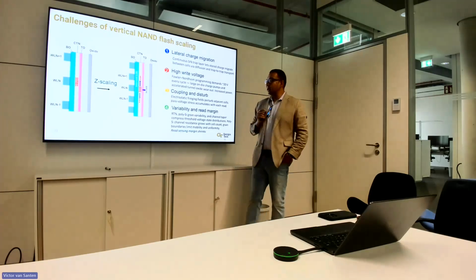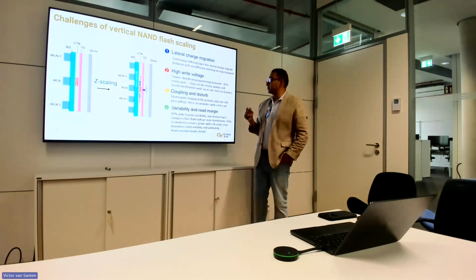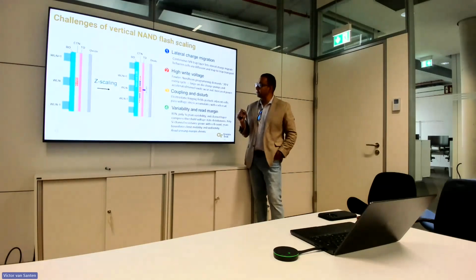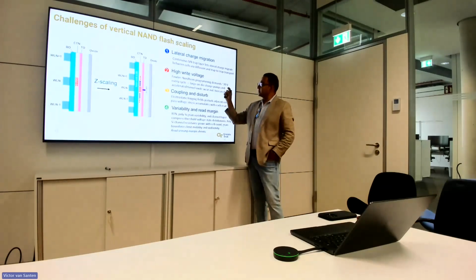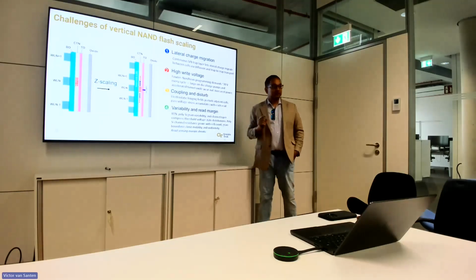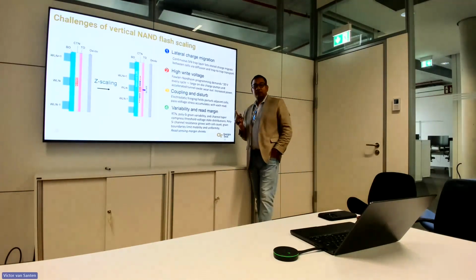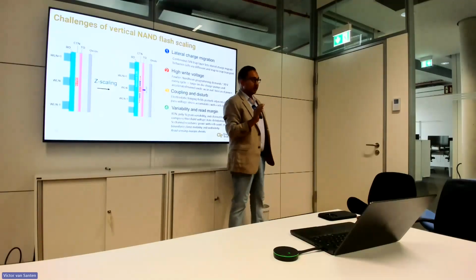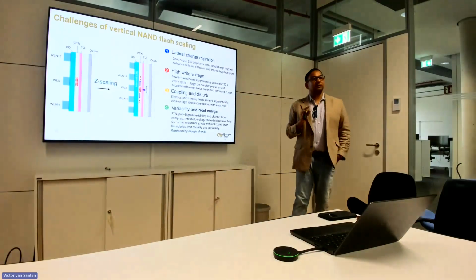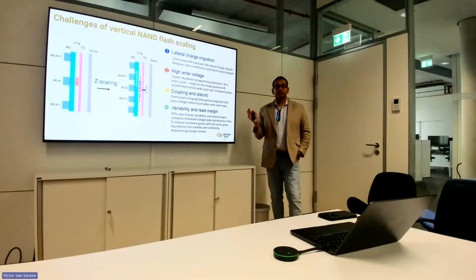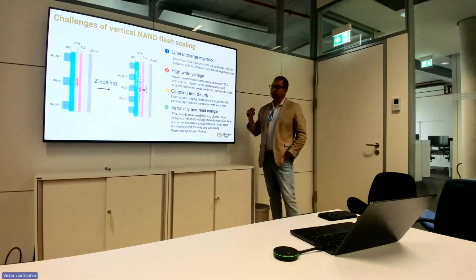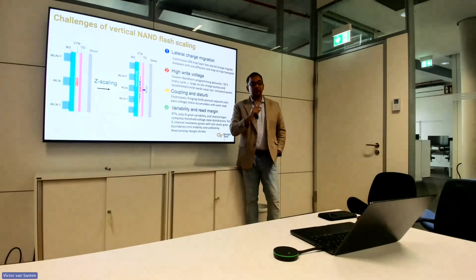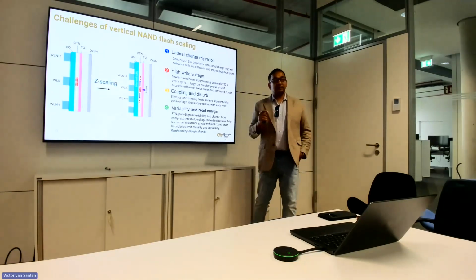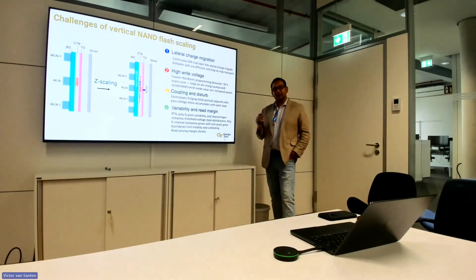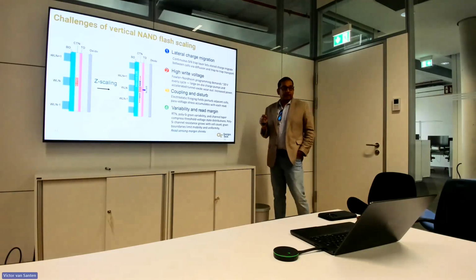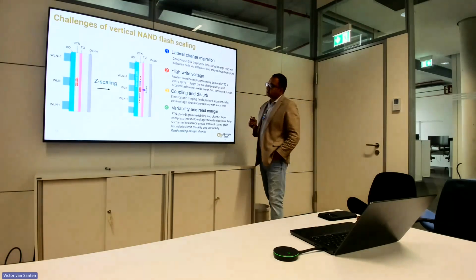Second thing is that I was actually very surprised when I started working on NAND flash technology at how high the voltage is. The voltage of NAND flash is of the order of 20 to 25 volts. It's humongous, right? On CMOS, we're talking about going to 500 millivolt or 200 or 300 millivolt. Here, the voltage is actually 20 to 25 volts. In high-end drives, it's probably much higher; I think it can go to 28 volts as well. So this is a very high write voltage.